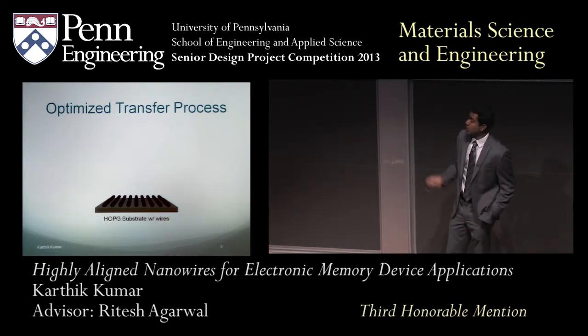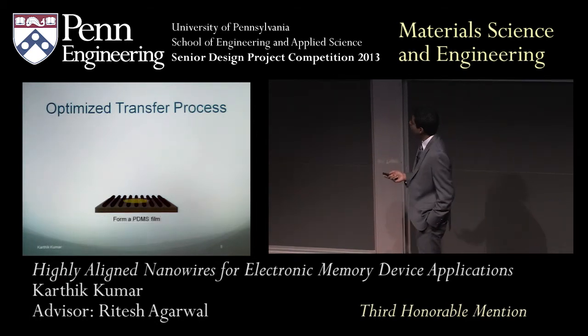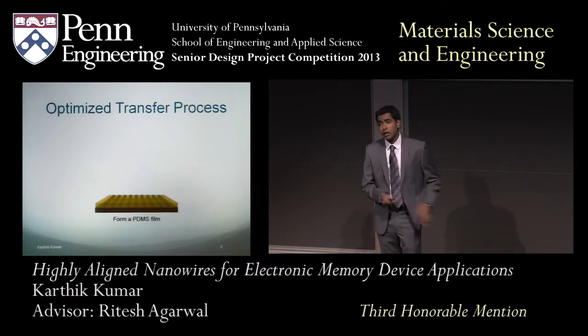So we start off with our HOPG substrate, which has nanowires on them. We then form a PDMS film right on the substrate.